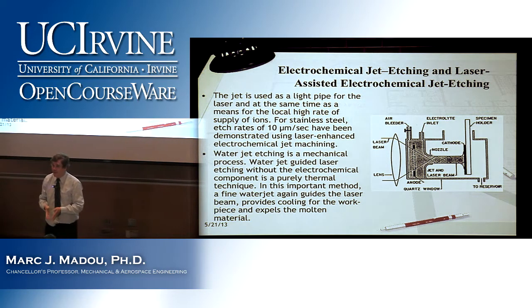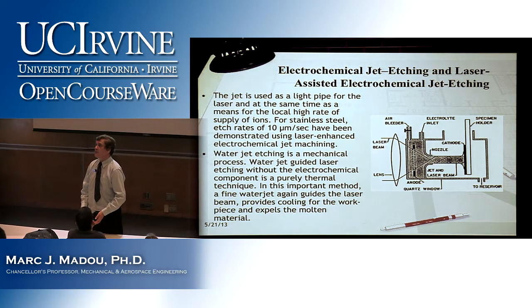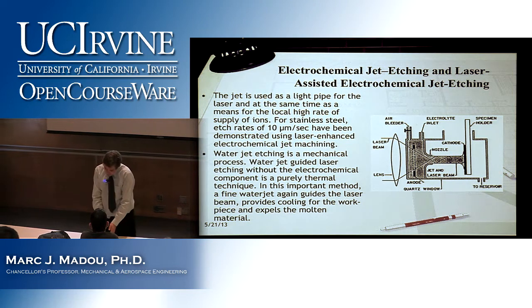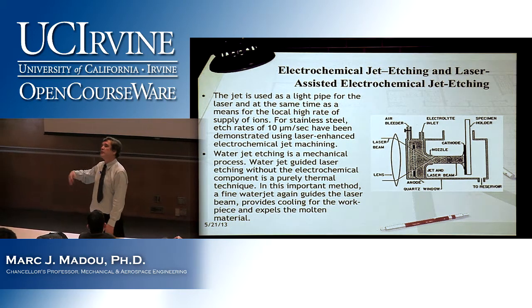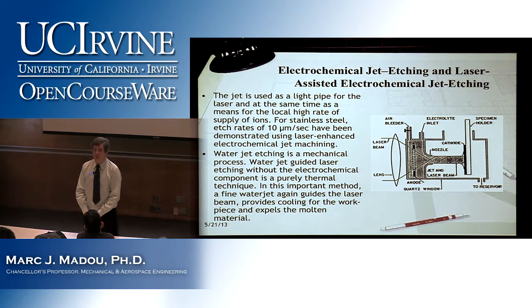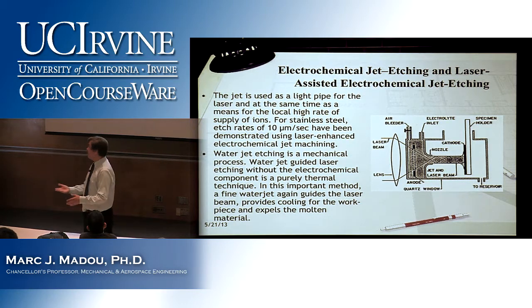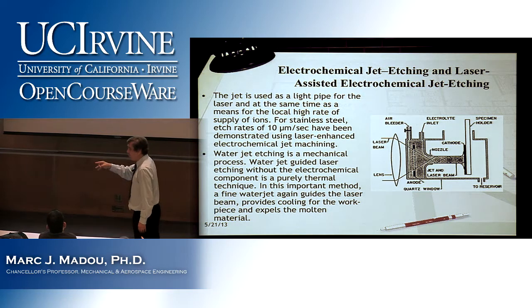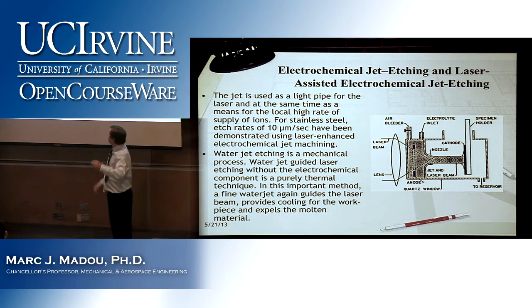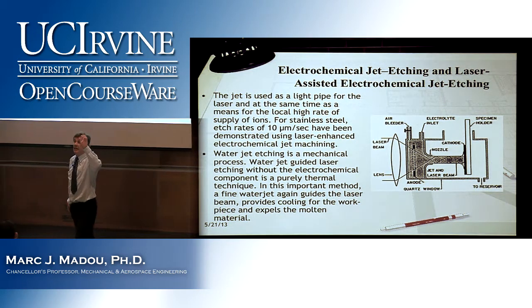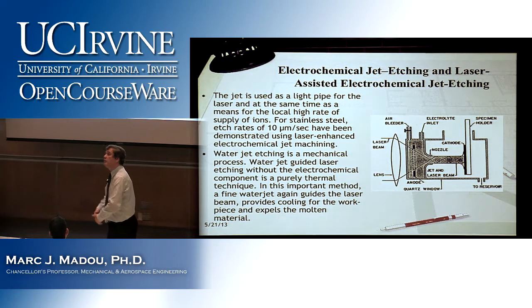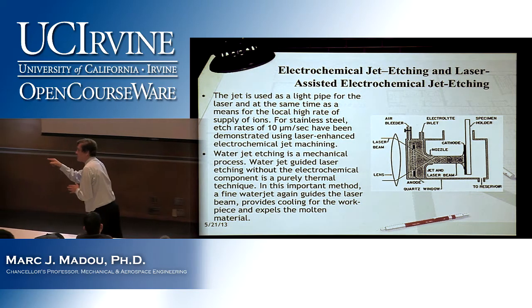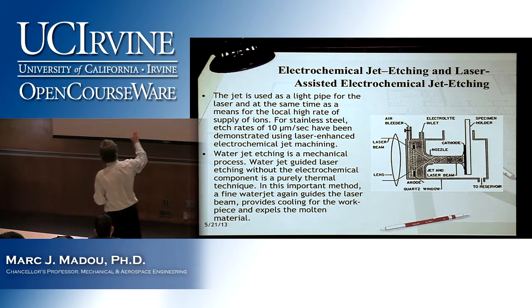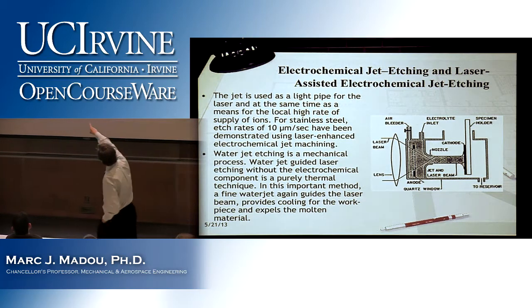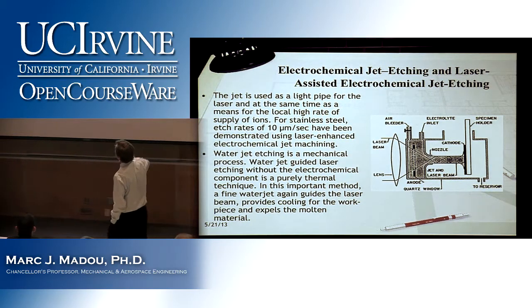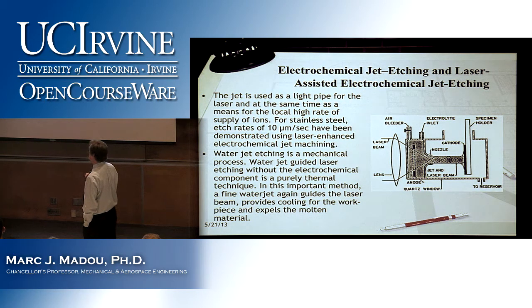Now the surface is bombarded with that light while doing electrochemistry at the same time, and you get a huge increase in efficiency. If you might etch something at rate 1 before, this will be 100 to 1,000 times faster. Same for plating. You can do this for etching very fast, but also for plating. Let's say you want to write copper lines or gold lines with this machine. You just put the right metal in your solution, and then your workpiece will not be the anode, it will be the cathode, because you're now depositing the metal. The local heating of the laser on the substrate increases the deposition rate dramatically. So it's a very good way to get very fast etch rates. For example, for stainless steel, etch rates of 10 micrometers per second have been demonstrated using laser-enhanced electrochemical jet machining.